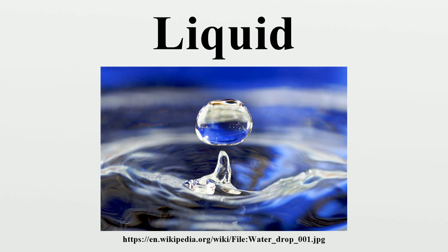On supercooling a liquid towards the glass transition, the crossover from liquid-like to solid-like response moves from GHz to MHz, kHz, Hz. Equivalently, the characteristic time of structural relaxation increases from ns to μs, ms. This is the microscopic explanation for the above-mentioned viscoelastic behavior of glass-forming liquids.